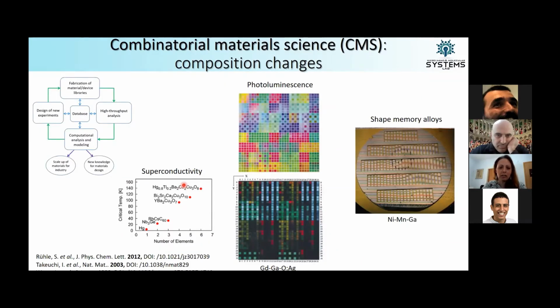And this is exactly the method that I use to do my research, which is combinatorial material science. This is basically a cycle type of research where you have a variety of steps, which include high throughput fabrication and high throughput analysis, inserting information into a database and designing of new experiments from all of this. Combinatorial material science has proven to be very good when looking at compositional changes of material and discovering new materials, for example, for photoluminescence, shape memory alloys, or high TC superconductors. So you can see that as you increase the complexity of the elements, so more elements in this case, you actually get interesting results.